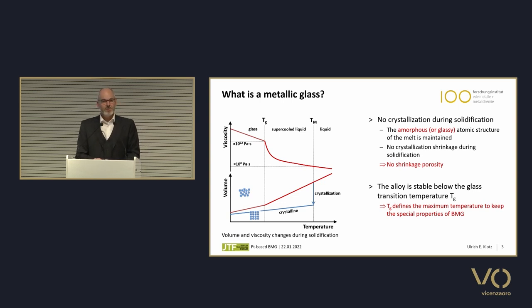But bulk metallic glasses do not show such a sudden drop of volume. Instead, they show a continuous shrinkage until the glass transition temperature is reached. And after that, the volume change is even slower. So due to this continuous and slow change of volume with decreasing temperature, there will be no shrinkage porosity when cooling these alloys. Well, and the material is not crystallizing, therefore there is no crystallization shrinkage, but instead the viscosity of the melt, which is plotted here, is steadily increasing, and with decreasing temperature it's exponentially increasing, so the material gets somehow solid, although this amorphous structure is still there.